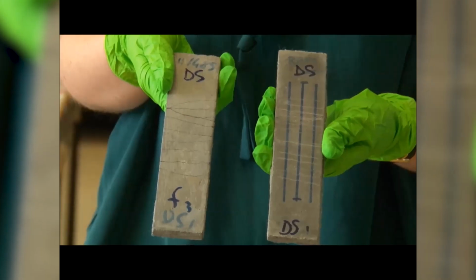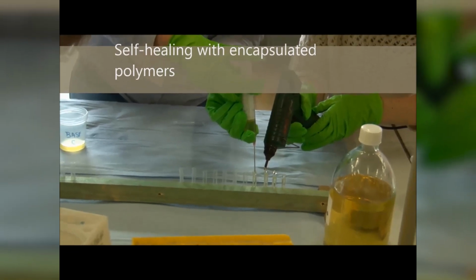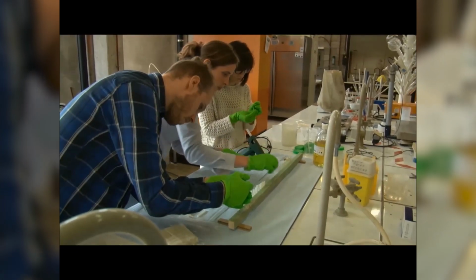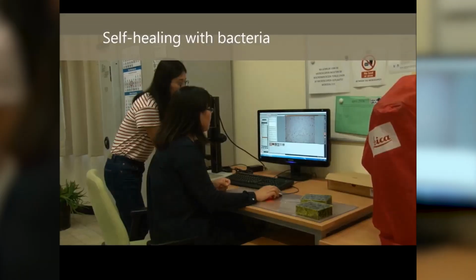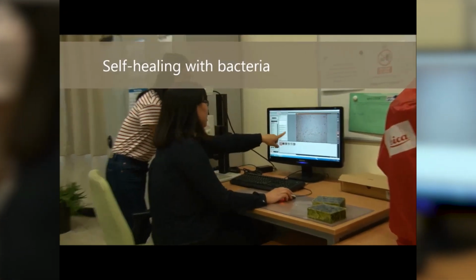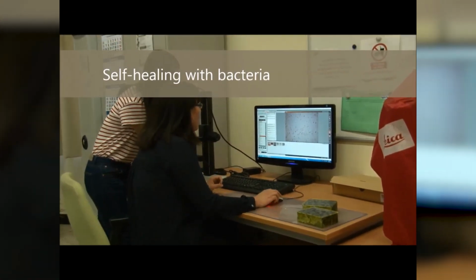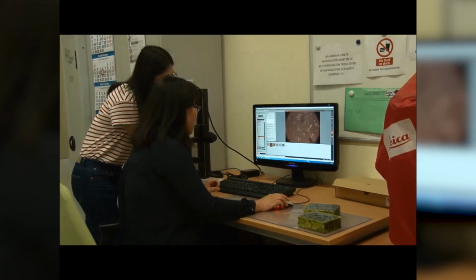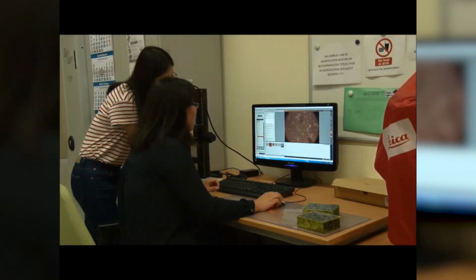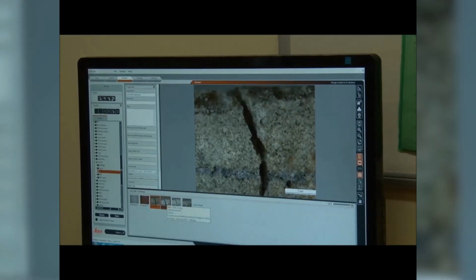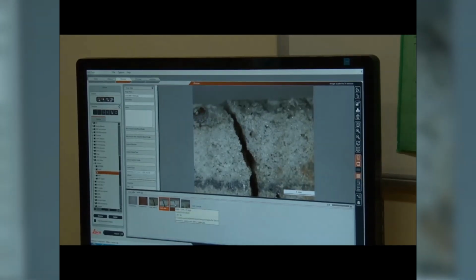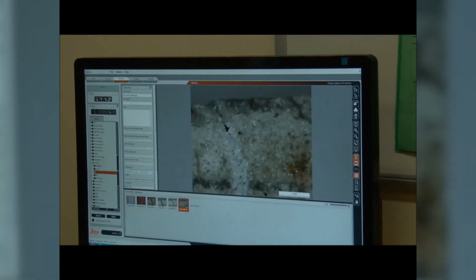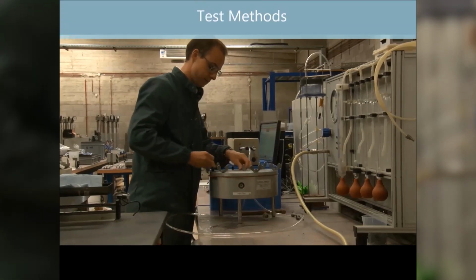They approach the self-healing by the use of 3 different strategies: superabsorbent polymers, which can absorb a huge amount of fluids and provide them to promote autogenous healing in concrete, encapsulated healing agents, which will be released upon a crack, and bacteria, pre-added into concrete during mixing. They will become active and precipitate calcium carbonate after a crack happens.